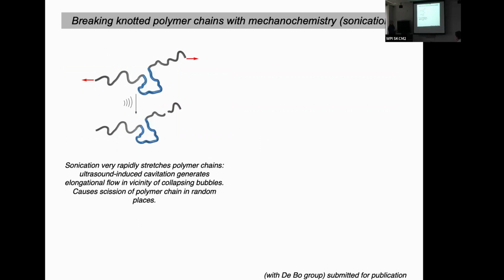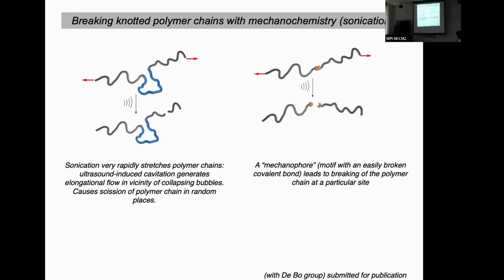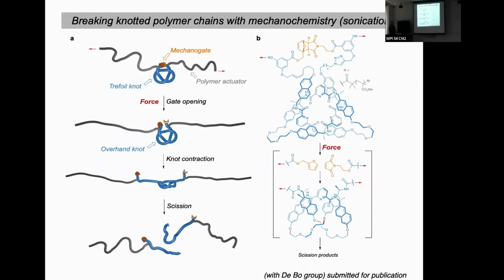So polymer chains can be put under stress using sonication in what's called mechanochemistry. If you sonicate polymers, it will elongate them in collapsing bubbles that puts a lot of stress on them, and they'll fracture at particular points. So you can add to these polymers groups that will undergo chemical reactions under stress, and those are called mechanophores, that will break easier than other kinds of functional groups, and then get well-defined breaking points. So what we did is that we made one of our knots, one of these lanthanide templated systems, and then we closed the ends of it with a mechanophore, something that will be broken by a strain.